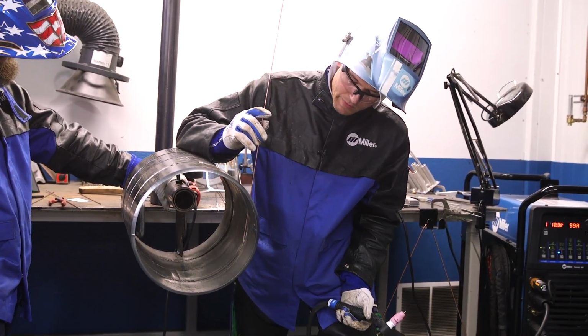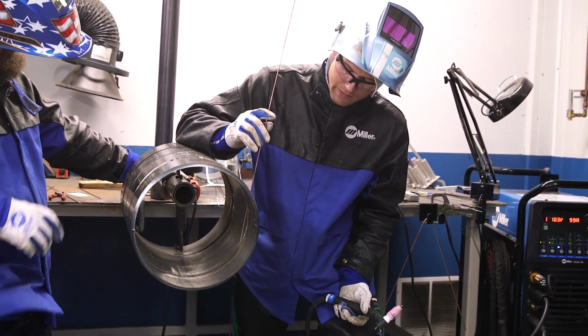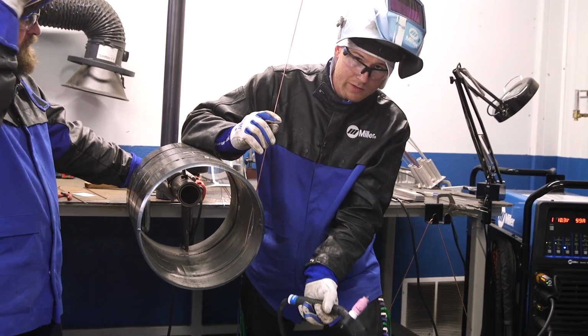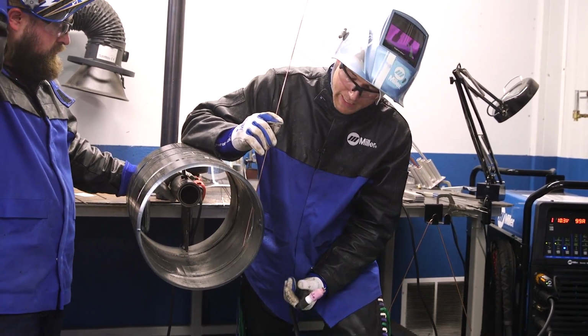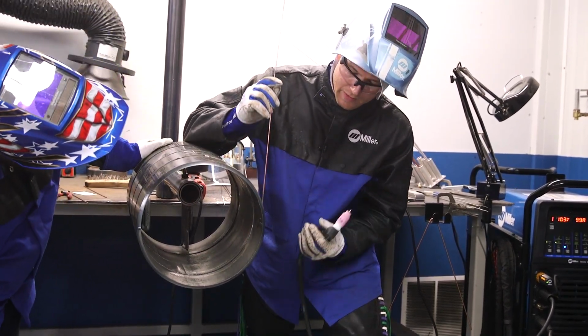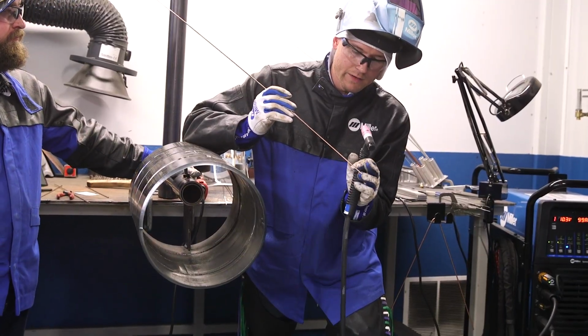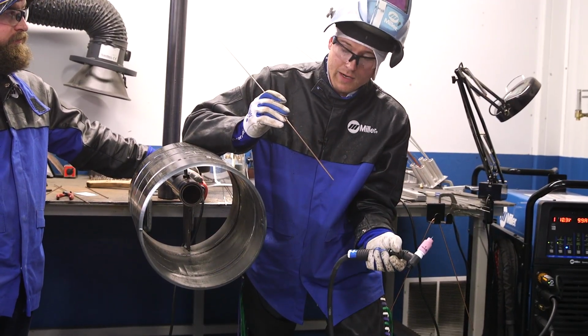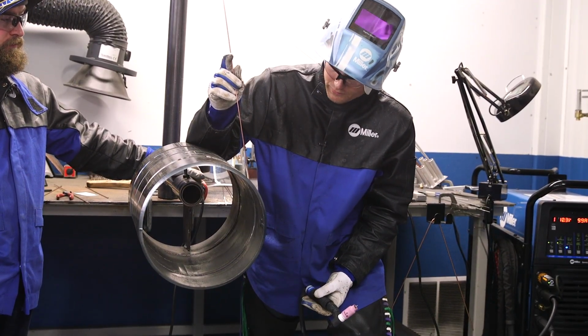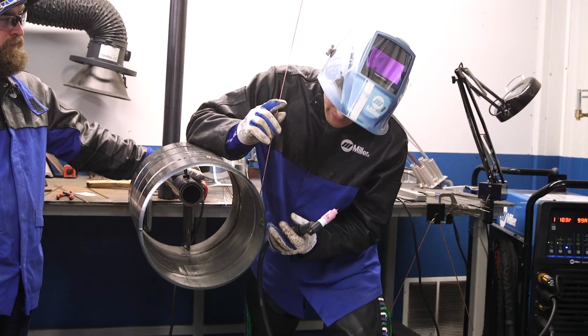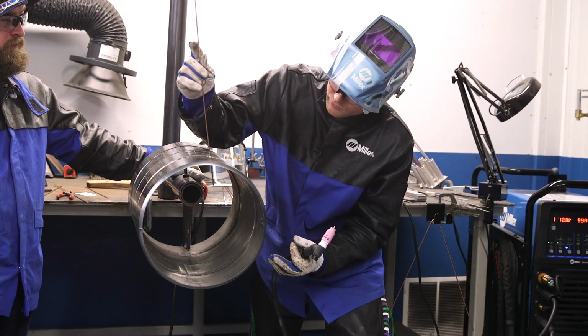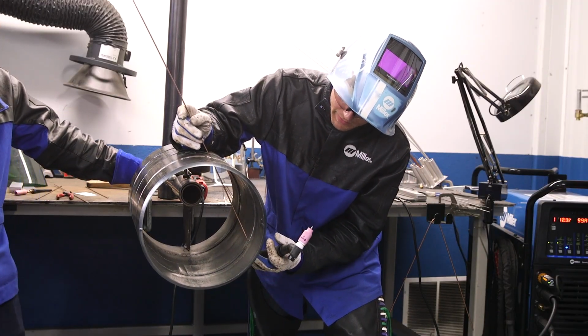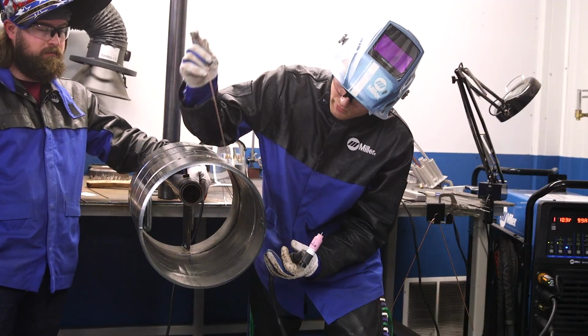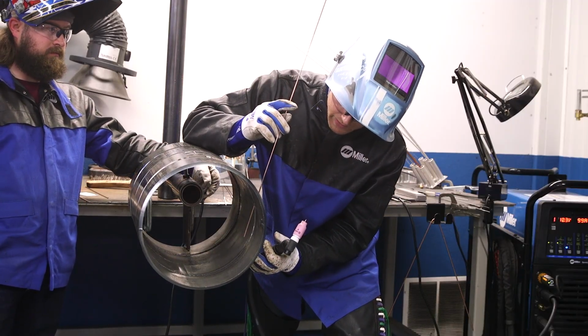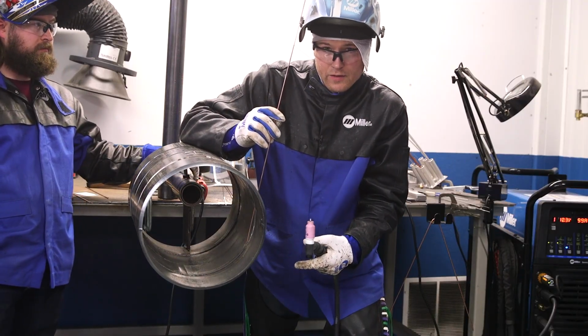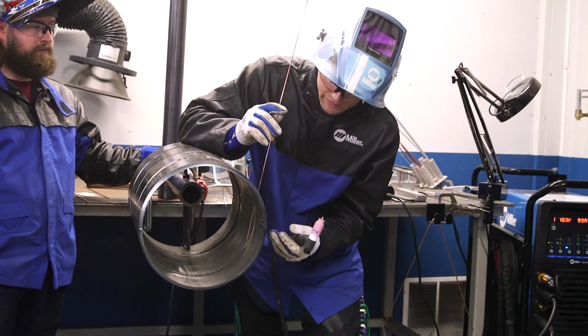So say, for example, if I'm feeding at this angle, if I'm not too careful, the internal leading edge might still be a solid before it turns to a liquid, and I might slide down a little bit past it and actually melt off prematurely off the side of the filament metal, and that's when you get the rod stubs. So one way around that is to watch the internal leading edge. You can also change the angle so it's more direct on, melt off the tip of the filament metal, or else you can watch your external leading edge and then the split second later the internal leading edge. So it's basically you're lining up your line of sight.